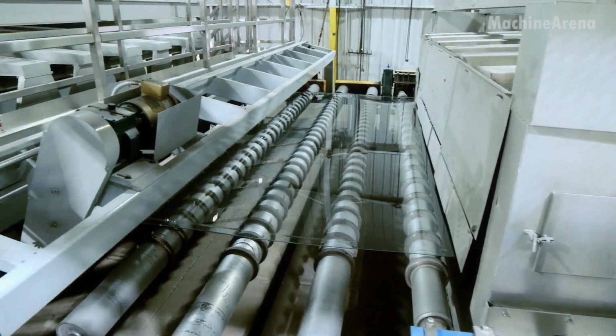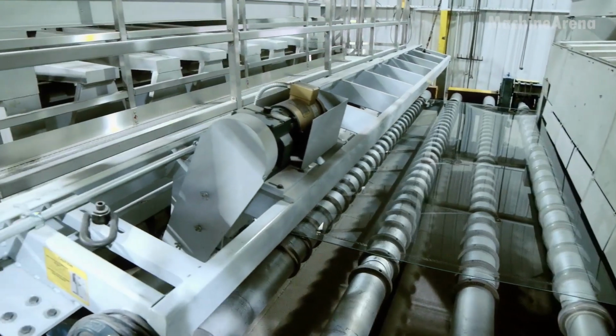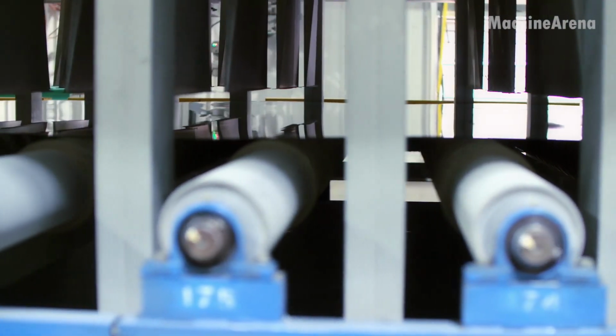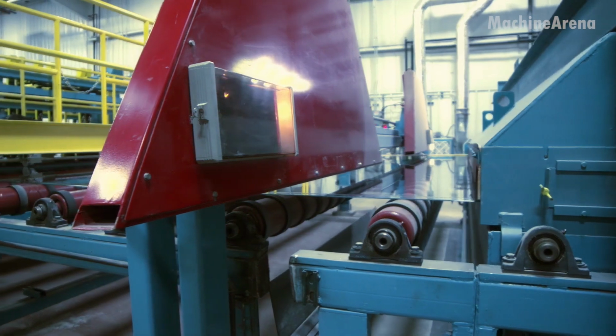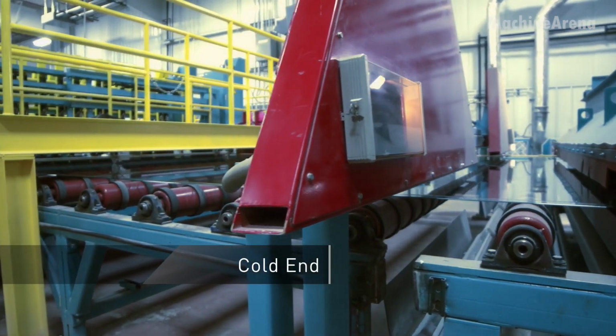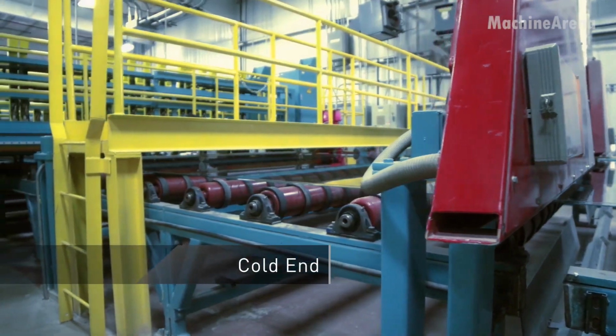The glass ribbon is carefully controlled in both speed and width as it travels across the tin bath. It is then gradually cooled in a special annealing zone, a long, temperature-controlled tunnel that reduces internal stresses and hardens the glass without causing distortion. This stage is essential to ensure the final product is stable, flat, and safe to handle.